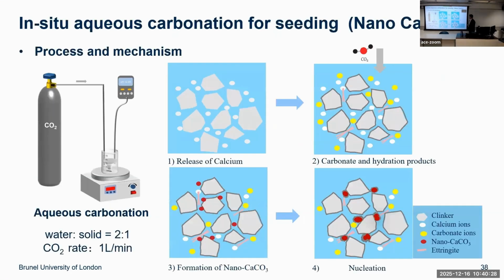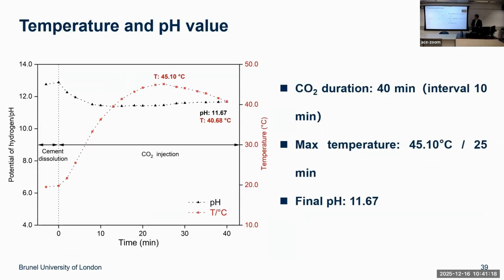Okay, so the mechanism is that through this aqueous in-situ carbonation, calcium is released, and at the same time the hydration generates carbonates and hydration products. Then the reaction with this calcium and carbonate generates nano-scale calcium carbonate, and this nano-scale calcium carbonate further acts as a nucleation site to hold C-S-H, and also fills the macro cracks and macro pores. This improves the microstructure and further improves the durability and strength. Okay, so this is just the mechanism. So we need to do the way we use that.